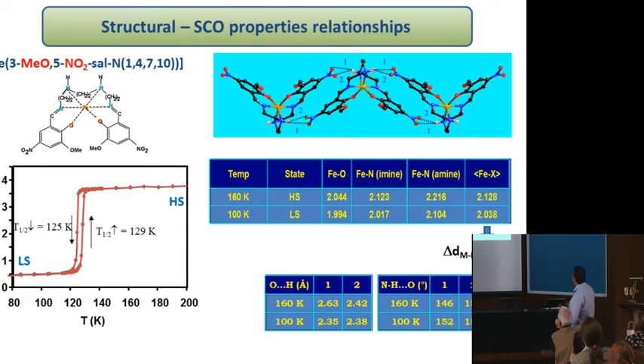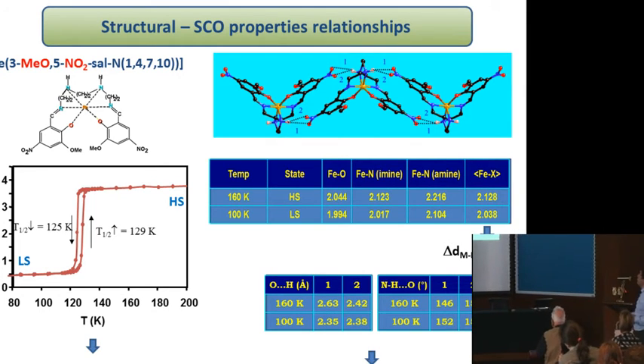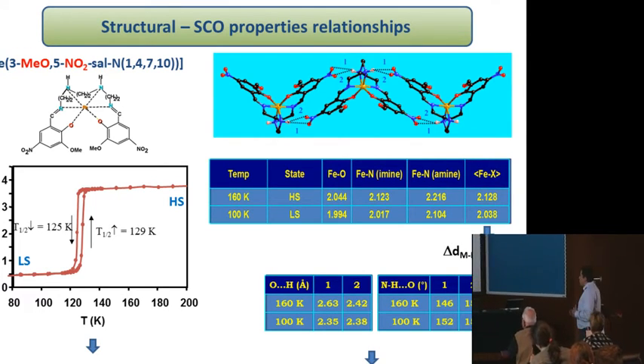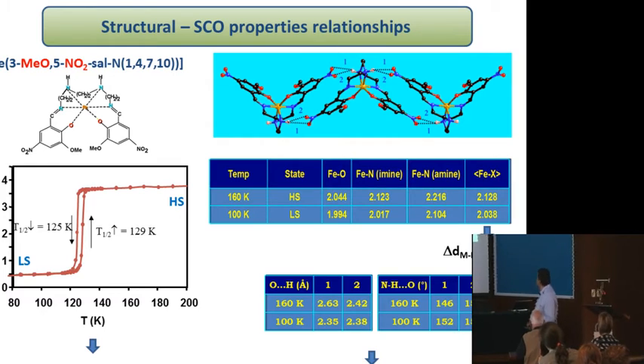Again, now if you try to have the correlation, we understand. Here we have the same geometry, the same structural organization, and now we have not strong interactions, but you have 4 hydrogen bonds in this kind of molecule. So this can explain the abrupt transition in these complexes. When you have a stronger hydrogen bond network, we obtain complete and abrupt transitions.